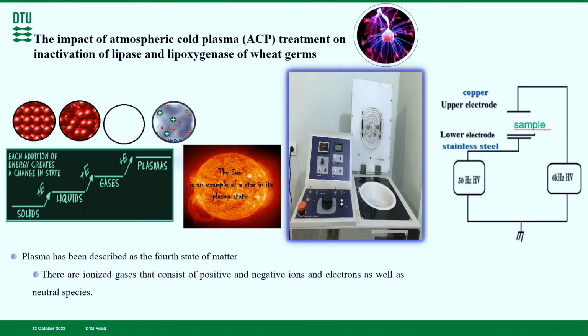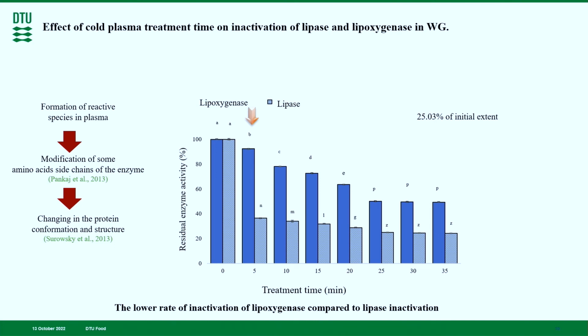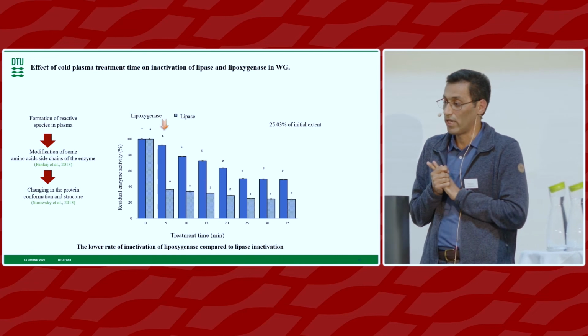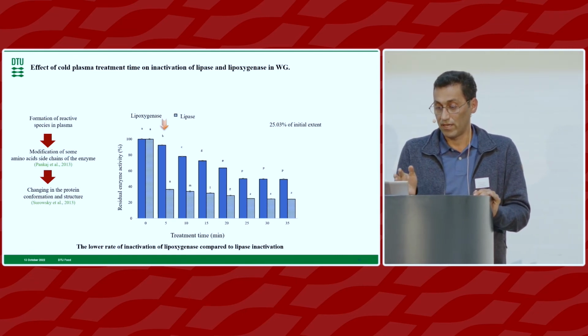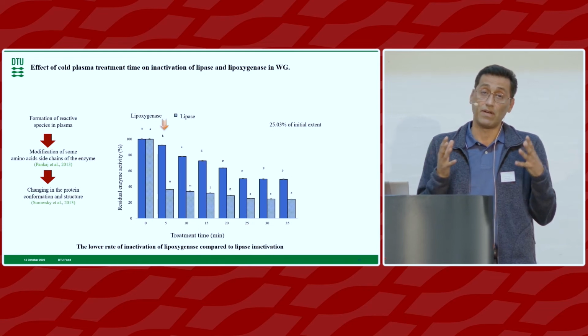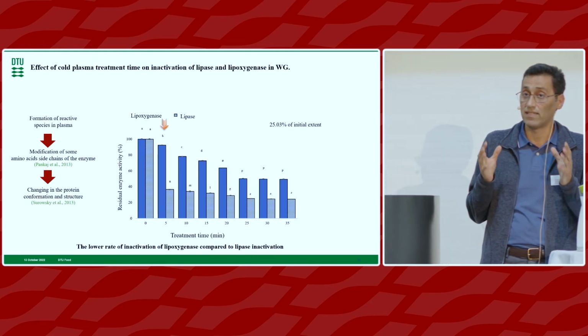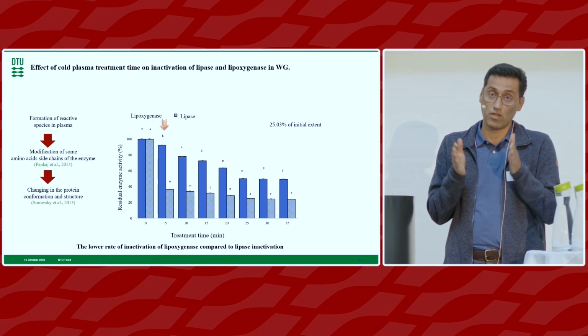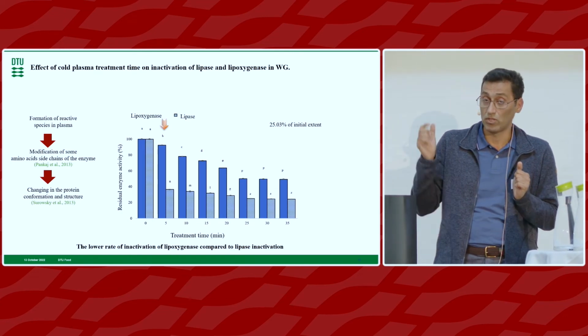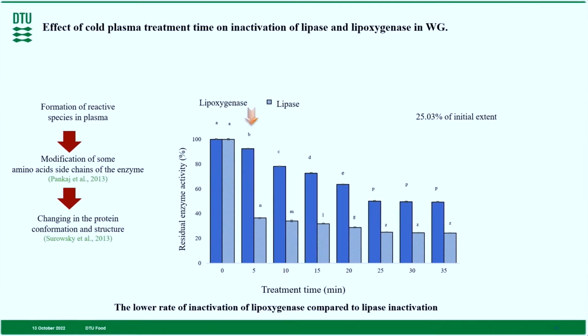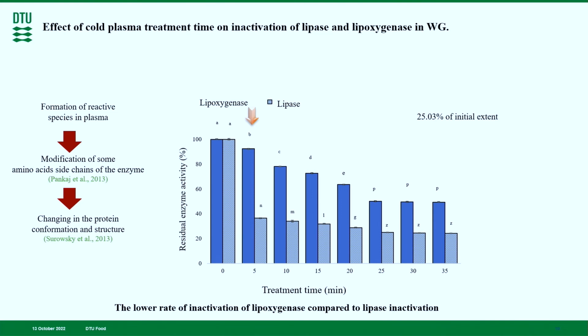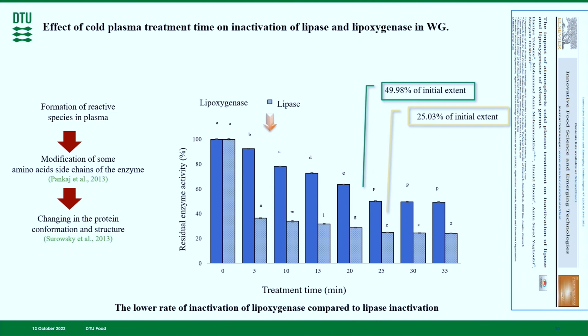But we use these reactive species to inactivate enzymes. In a project, you know that wheat germ is very nutritious, but unfortunately we have lipolytic enzymes in wheat germ, which makes its shelf life so limited. So we used this cold plasma to inactivate these lipolytic enzymes, two of them, lipase and lipoxygenase. As you can see, we have a significant reduction in activation of these enzymes, but we noticed that the sensitivity of different enzymes to this treatment is different.